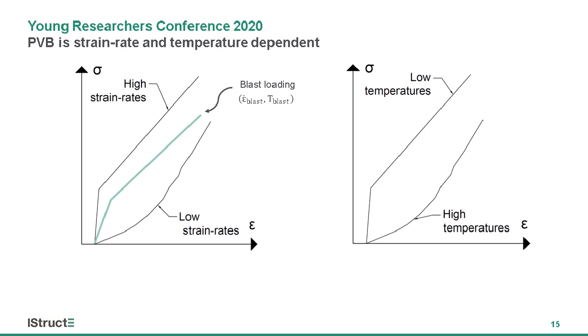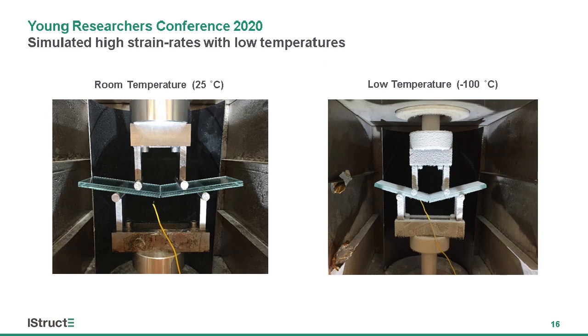PVB is also sensitive to temperature, and using previous experimental work, I demonstrated that there's a time temperature dependency similar to many other polymers. Therefore, the PVB response at high strain rates can be simulated with low temperatures by deriving a time temperature mapping equation. This uncouples inertia effects and allows investigation of the pseudostatic bending moment capacity.